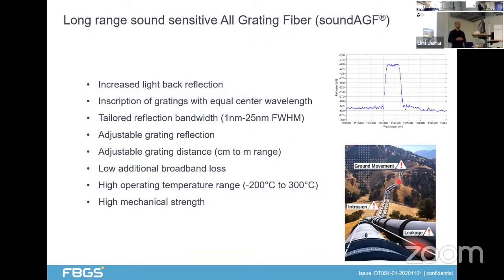This is especially important for the handling process, because usually the fibers are in the field, not directly where they are made. They need to undergo a cabling process and get additional protection. During that, if you would use strip-recoated gratings, the probability of fiber breakage is quite high. Okay, this was for the application around enhanced backscatter fibers.